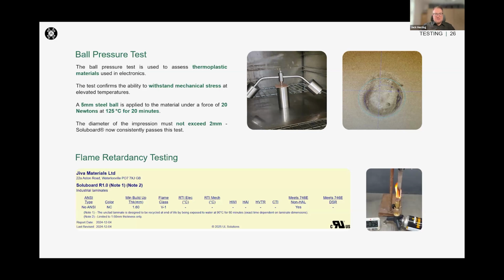On the right hand side, you can see that this was a failure. This was something which we had to deal with for a number of months, but we're now consistently passing this test every time, and we don't have any impressions above the 2 millimeter, which is the pass rate. In terms of flame retardancy, we currently sit at a V1. For those familiar with the test, it's all about the amount of time that it burns.